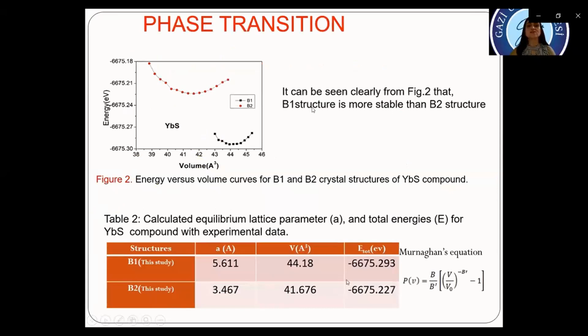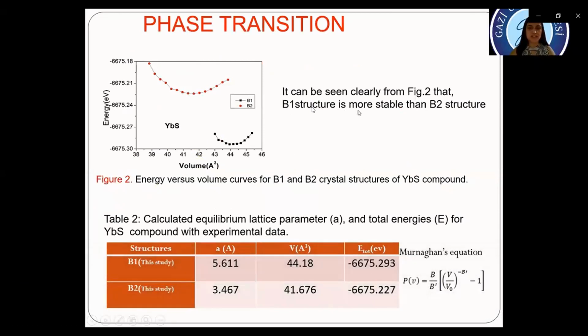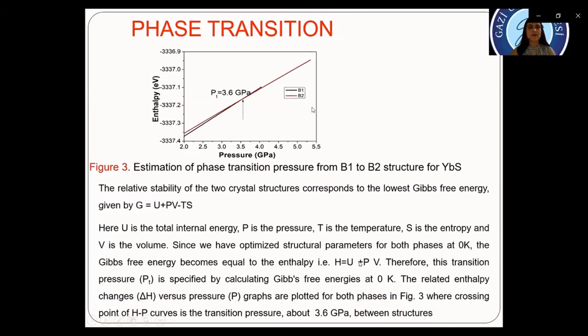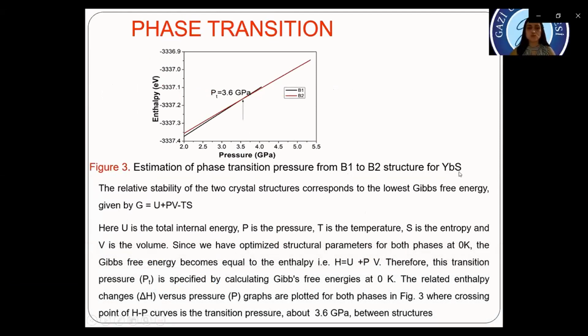Phase transition. It can be seen clearly from figure 2 that the B1 structure is more stable than B2. We calculated these parameters, the lattice parameter, volume and total energy, for B1 and B2, and you can see the phase transition. Figure 3: estimation of phase transition pressure from B1 to B2 structures for YbS.